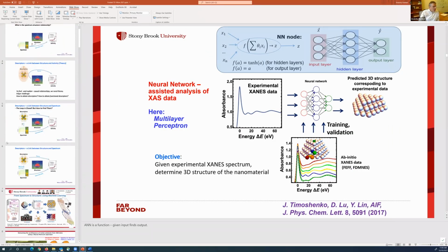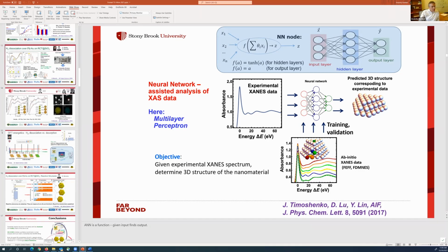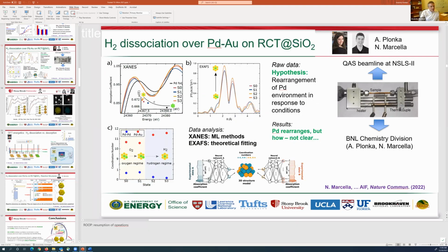Yeah, I mean, if you have the oxide, you can guess how many oxygens you have there, and then compare how big the signal is. Assume for each palladium dimer at the surface you have an oxygen. Could I still see this by just scaling? Let me show you just temporarily the same presentation, but with EXAFS, so you will see where oxygen would have been, because EXAFS is more direct, right? So this is the data, and you see where my cursor is. If oxygen were to be found, it would be somewhere in this range.